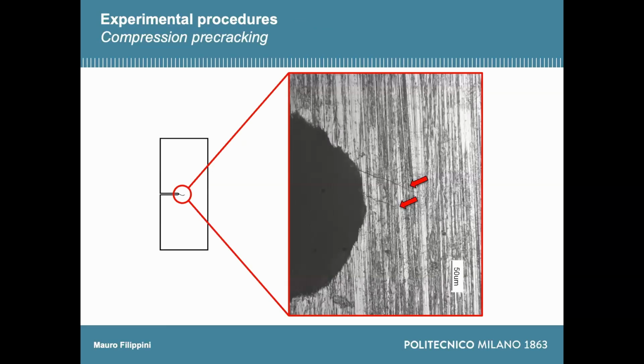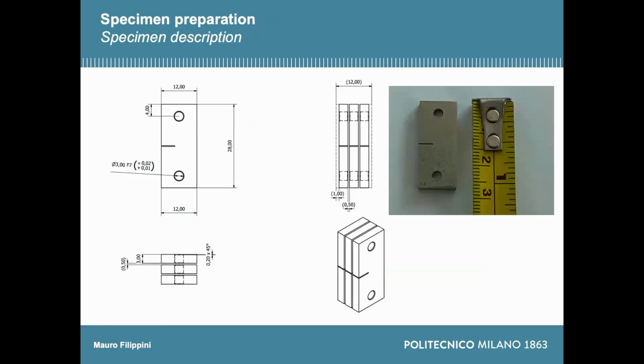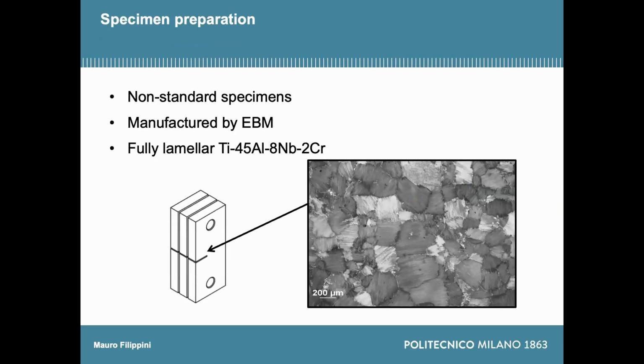These are the cracks that are generated by compression pre-cracking. And so there are tiny cracks ahead of this notch. And then after pre-cracking, the whole specimen, which has a total height of about 28 millimeters, we sliced in three small specimens. We produce a hole which is slightly beveled, and we started with a conventional fatigue crack growth test.